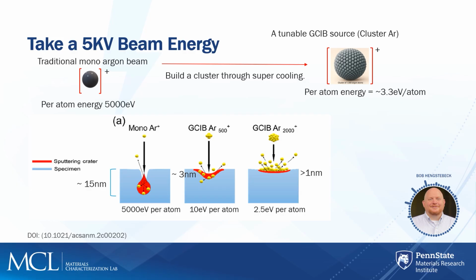And as we're going to show in the images, in this image A, which is a slide that I have borrowed from a source that's listed here, if we were to use the standard monoatomic gun and sputter into the material, the actual sputtering process is something called a collision cascade. And we're going to show an example of what that looks like in the next slide. But the actual sputtering occurs by essentially uplift of the material from well below, pushing the material out. And those interaction depths, let's say at 5 kV, are about 15 nanometers.